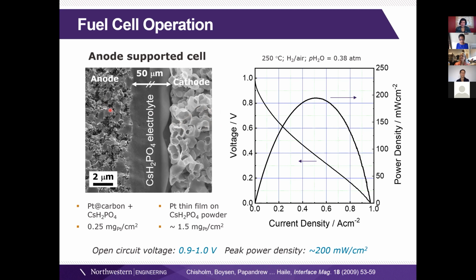At the anode side, we have a composite as well, which is the platinum on carbon. This is commercial material, and then we mix that in also with the electrolyte, so we have good proton conductivity. So we have relatively low platinum loading on the anode side, but quite a high platinum loading on the cathode side. This is our typical fuel cell performance.